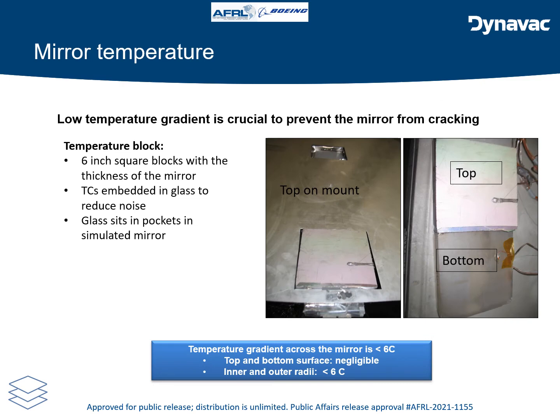Low temperature gradient is very crucial to prevent the mirror from cracking. We did a lot of mathematical simulations in order to understand the temperature gradient, and experimentally we confirmed it by using 6-inch square blocks similar to the thickness of the mirror, and we epoxied thermocouples onto them to minimize the noise. These blocks were mounted onto the simulated mirror, and we processed them as we would process the mirror. We looked at the temperatures, and the temperature gradient between the top and bottom surfaces was pretty much negligible. We couldn't see any temperature difference.